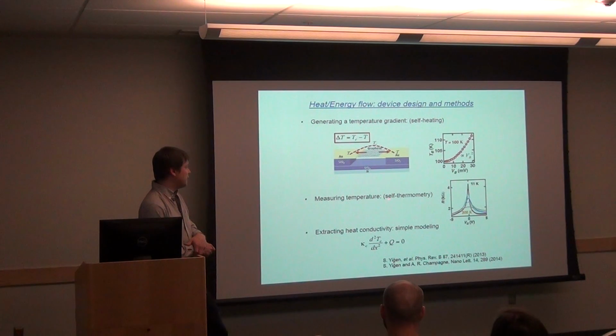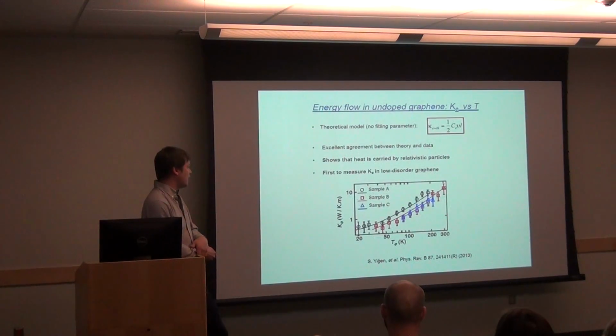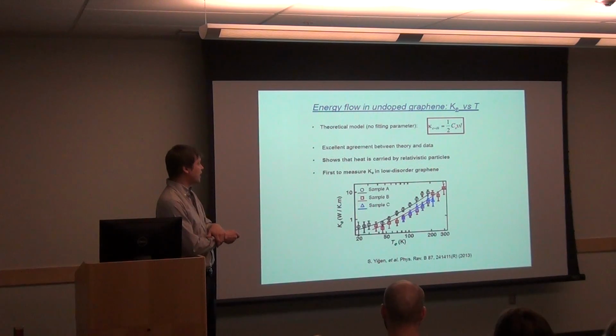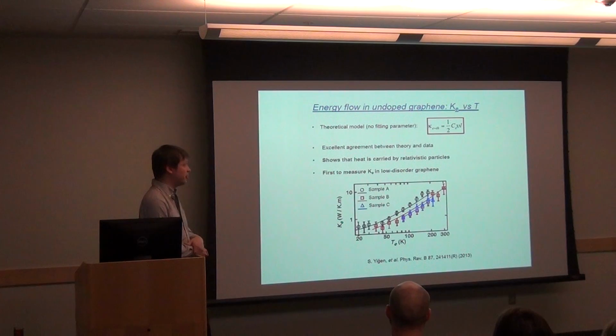And if we, well, that's the example. It shows here how the resistance changes with temperature. And then to extract the thermal conductivity, how hot it gets is telling you how easily the heat goes out. If it gets very hot, it means the heat didn't get out very easily. And if it doesn't get very hot, even though you're applying a lot of power to the system, then the heat got out. To solve this is a simple 1D heat equation in this case. And the data matched very well with theory. And it basically told us that the heat carriers were also Dirac particles traveling at the Fermi velocity.